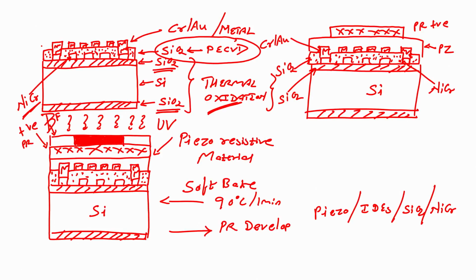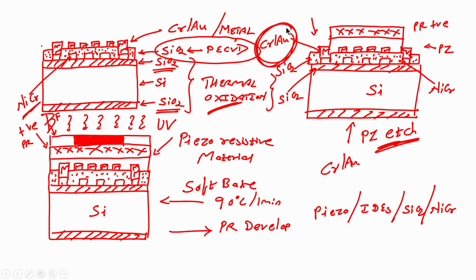So, now if I dip this wafer in piezoresistive material etchant, what will happen? It will etch the piezoresistive material, right. Suppose the etchant of the piezoresistive material also affects the chrome and gold, then what will happen? Once the piezoresistive material is etched from the area which is not protected by photoresist, it will start etching chrome gold.